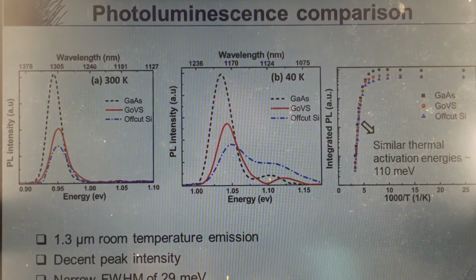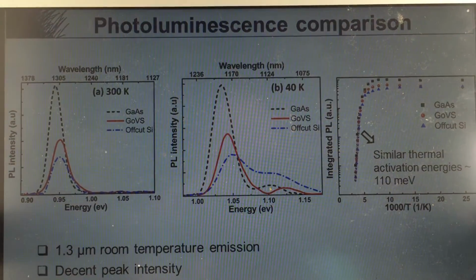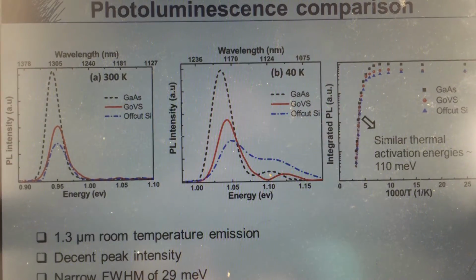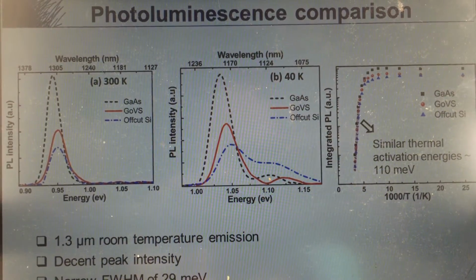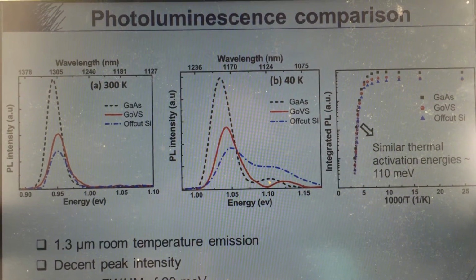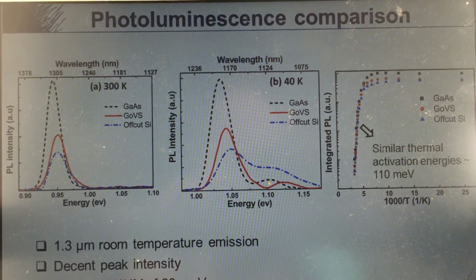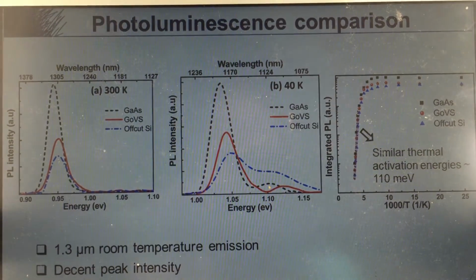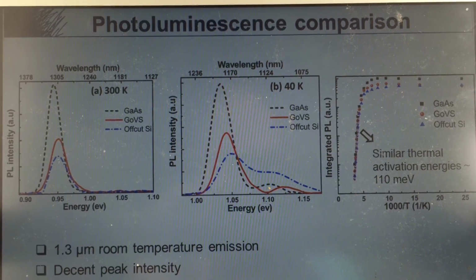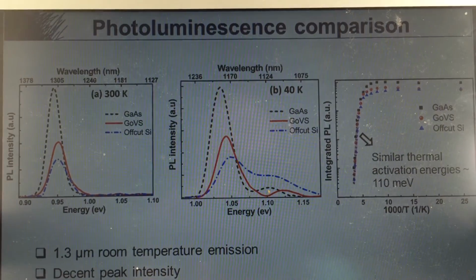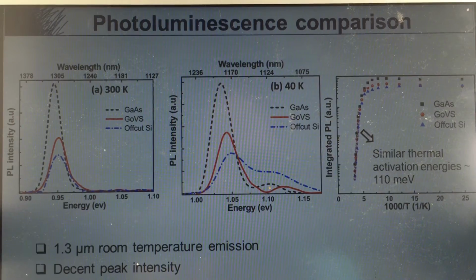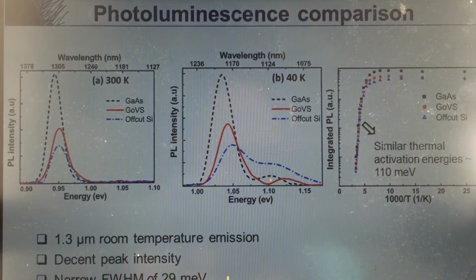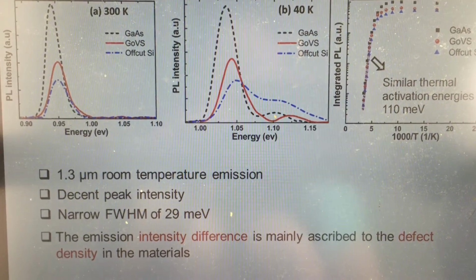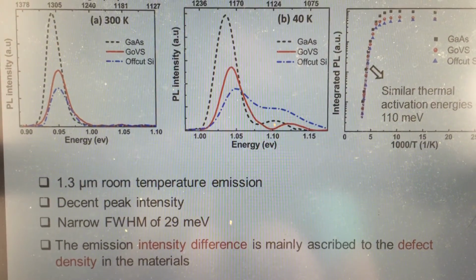To get more insights into the quantum dot structure, we extract the thermal activation energy through the integrated PL intensity as a function of the reciprocal of temperature. The thermal activation energies are close in value. The peak positions are also close in value, and these two indicate that the quantum dot structures on the three kinds of templates are basically the same. So, the emission intensity difference is mainly ascribed to the defect density in the materials.